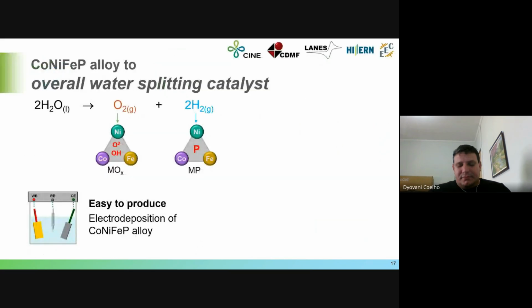How was it done? First, why study it? It is because this class of catalysts, like metallic phosphides, is used for overall water splitting, which means the catalyst can be used for the oxygen evolution reaction and for the hydrogen evolution reaction. There is a lot of literature reporting use of this one for both reactions. But actually, when this catalyst is used for the oxygen evolution reaction, the active site is not the metallic phosphide, because first a layer of oxide hydroxide is produced. And this metallic oxide hydroxide is the active site for the oxygen evolution reaction.